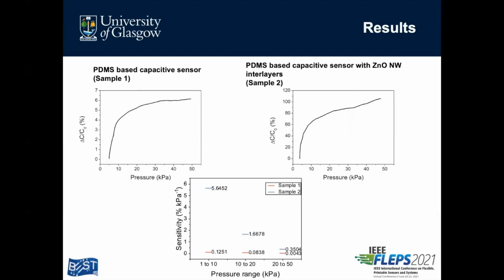We evaluated the sensing properties by measuring the relative change in capacitance at different pressure ranges up to 50 kilopascals. The standard PDMS-based capacitive pressure sensors revealed a relative change in capacitance of less than 7%. On the other hand, the sample with zinc oxide nanowire interlayers had that of almost 100% for the same pressure range. And from these results, we extracted their sensitivity at different pressure ranges, which are 1 to 10, 10 to 20, 20 to 50 kilopascals.